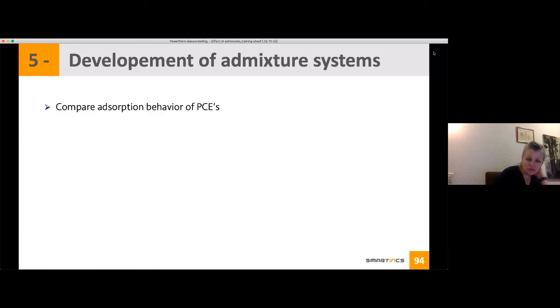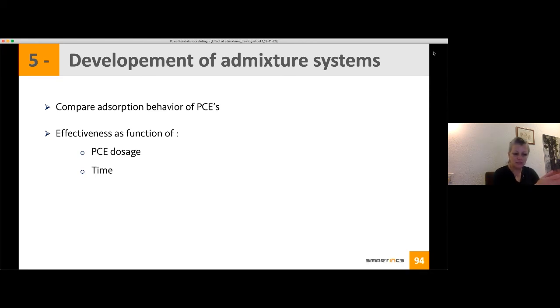So the message here, what we can use with the TOC, and it's more in a preliminary phase, is you can compare the adsorption behavior of your PCEs, and you can have also a database, and you know which is fast reactive, medium reactive, or for the open time. And you can also see what is the effect of the dosage. You can also see in time, will your admixture adsorb immediately? Maybe immediately won't do much, but you see that after 30 minutes, it will adsorb.